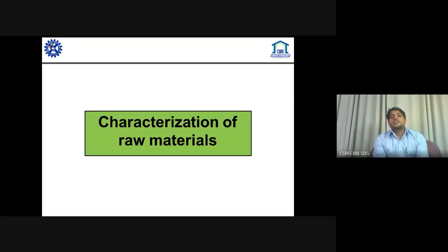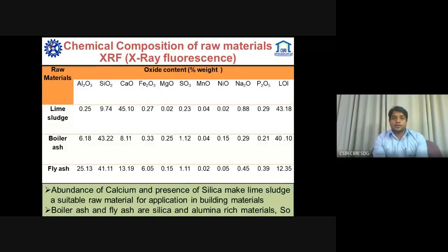waste. So for the characterization of raw materials, the XRF chemical composition of raw materials was performed. Lime sludge is basically calcium oxide, present at 45.10%. This is because the LOI, which is 43.18, is the carbon dioxide emitted, and the remaining is calcium oxide at 45.10%. If we take them together, it will be around 93 to 94% of calcium carbonate.